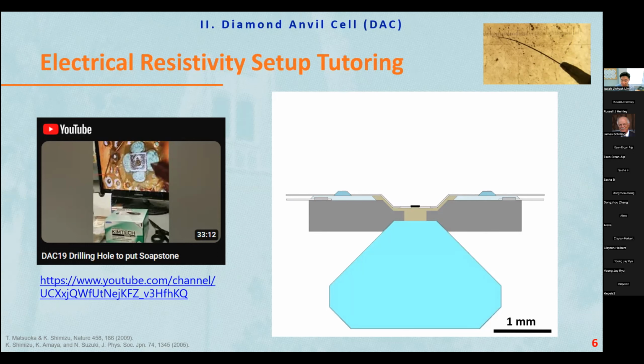so that we can put the sample nicely on top of this electrode. So this is the sample, and then put the ruby beside to measure the pressure of the sample. And the last part is just to squeeze the sample. In this way, you can get a very nice electrical resistivity measurement under pressure to check superconductors and other materials.